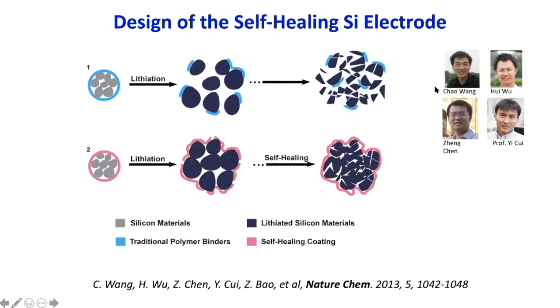I had two postdocs at the time from my group. One was developing self-healing material, one was an expert who had battery experience. So when we thought, well, these polymers can crack, then why don't we use self-healing polymers? Self-healing polymers, even if they crack, can still heal and recover the conduction pathway, ionic and electrical conduction pathway.